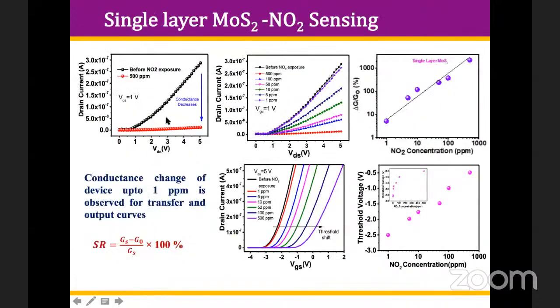And when we apply the gas, you can see this is without the exposure of gas. And when gas is put, around 500 ppm of NO2, it goes down very fast. So conductivity, you can say here, is decreased with the interaction of the gas on the surface of the MoS2 layer. And these are the variation with the concentration of gas. This is with 500 ppm, 100 ppm, 50 ppm. So that means the more concentration of gas there is, the more decrease in the conductance is obtained.